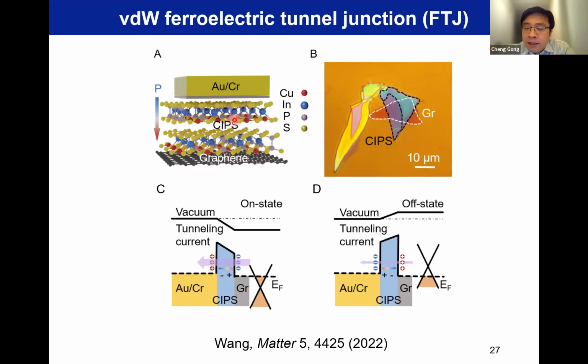So the first advantage is, as I said, this is a 2D ferroelectric, but with a minimum amount of defects. So the band gap for tunneling is very clean. For those defective oxides, you will have a messy band gap. So that will actually kill or damage the on-off ratio. The other one is there is no Fermi level pinning between this insulator and this graphene electrode. If you have Fermi level pinning, that will also weaken or even negate the ferroelectric control of band alignment.